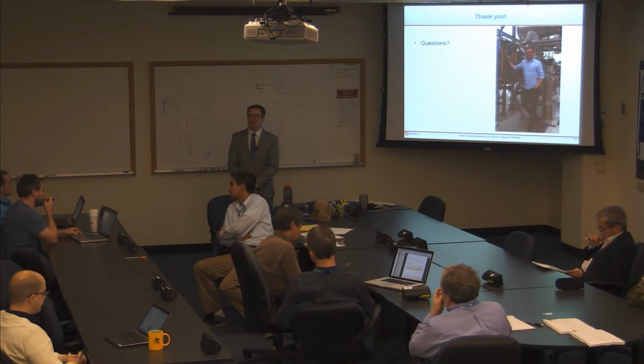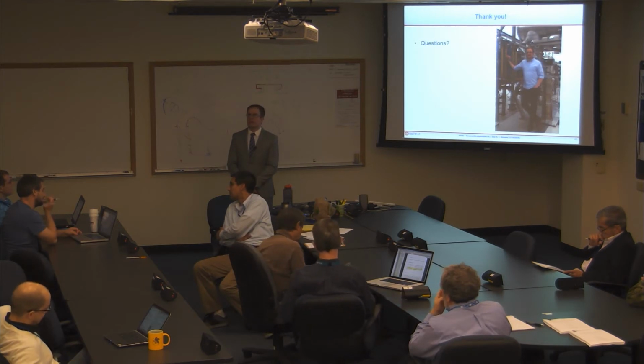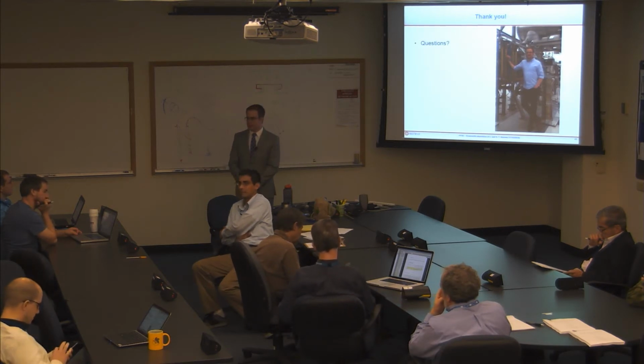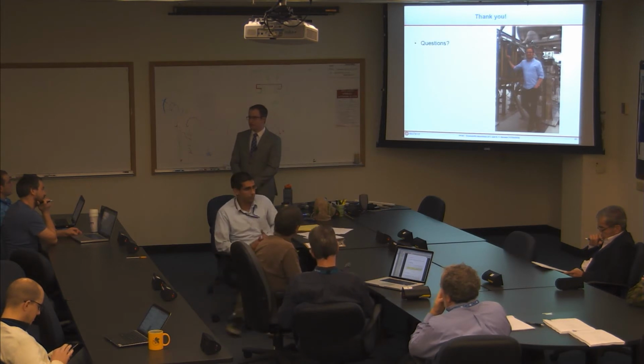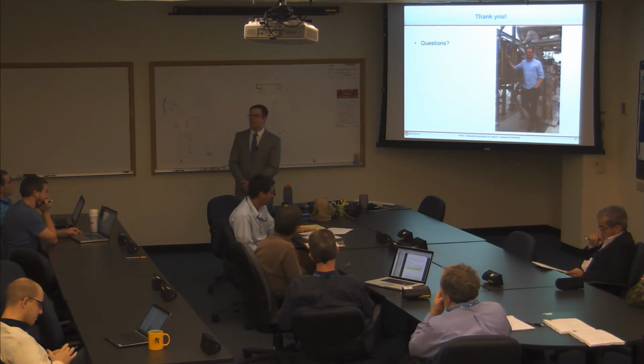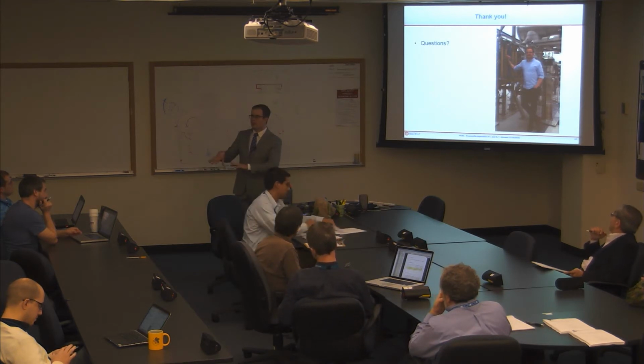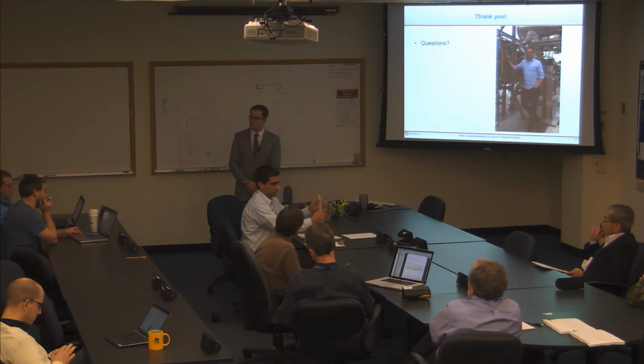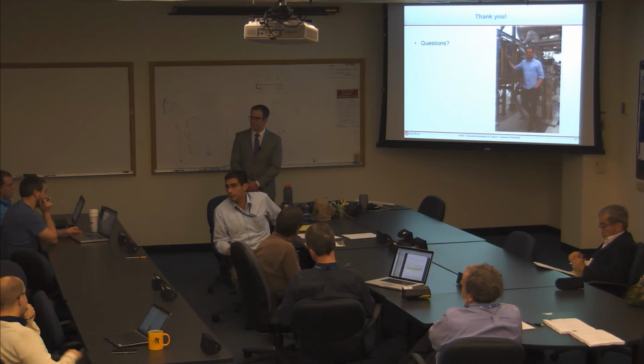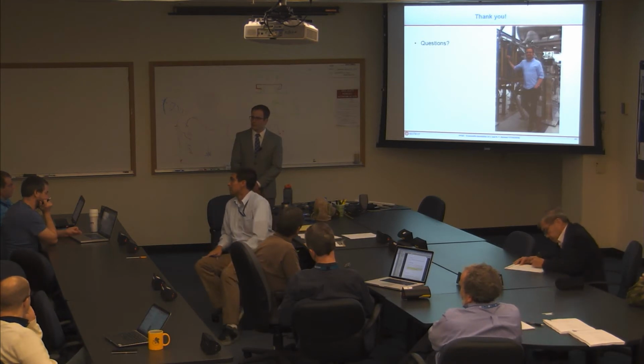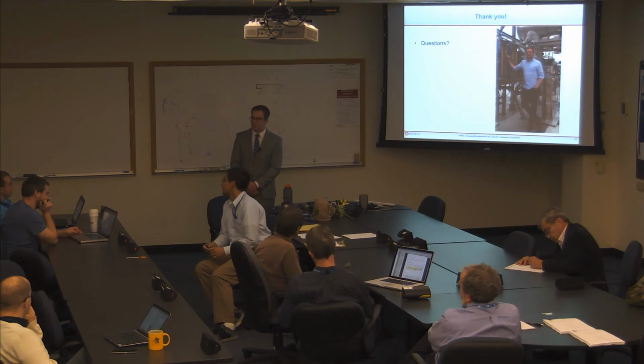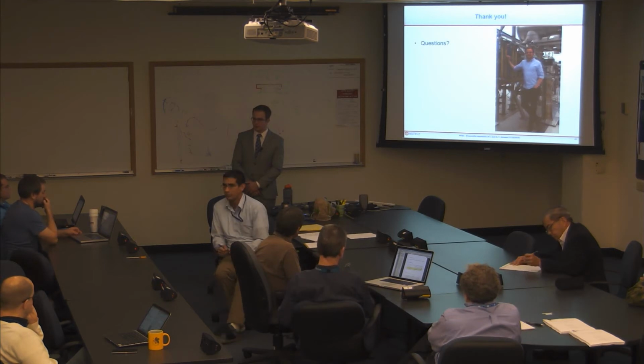I guess the thing is that once the lithium melts, that's going to start diffusing into the lithium surface. So maybe there might be a small range before the melt layer breaks through the coating that you could see a difference, but I didn't look for it. I think there's some papers I've read that show that oxygen stays on the surface of liquid lithium just by free energy. The segregation effect? Yeah. So maybe it would last a little. Again, we don't see oxygen on the spectroscopy measurements.